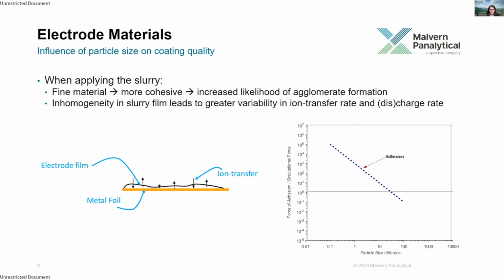So this slurry is then applied to the metal foil to ideally form a nice uniform electrode film. So this means we can also look at the effects of the particle morphology on the coating quality. As particles get smaller, they're more likely to stick together, as shown by the graph on the right. So this means that the more fine material you have, the more likely you are going to get agglomerates. So this increases the chances of getting inhomogeneities in the slurry film, which has potential to lead to greater variability in the ion transfer rates and the charge discharge rates, which ultimately is going to impact the battery lifespan.